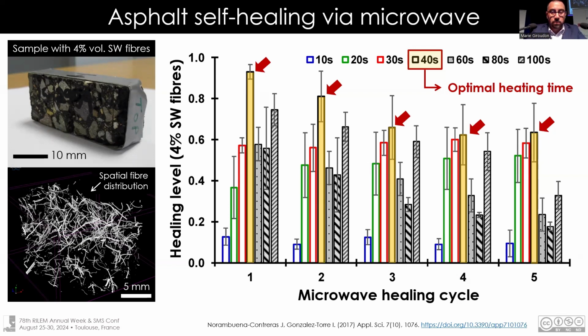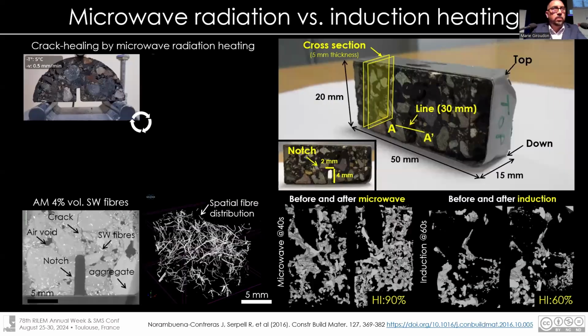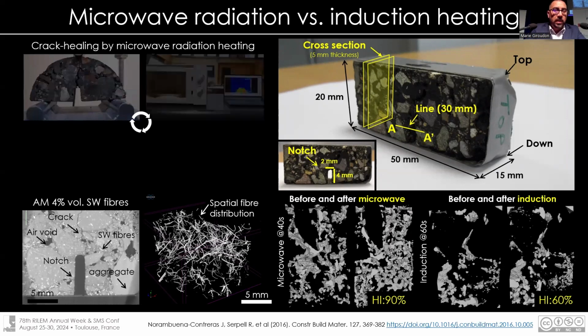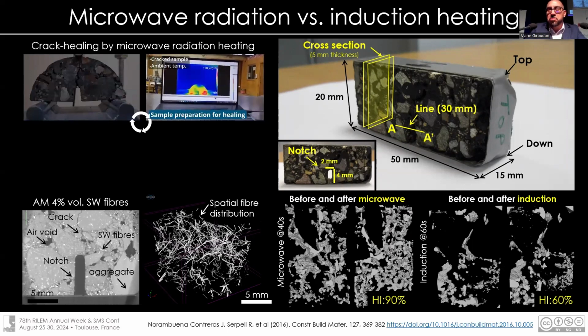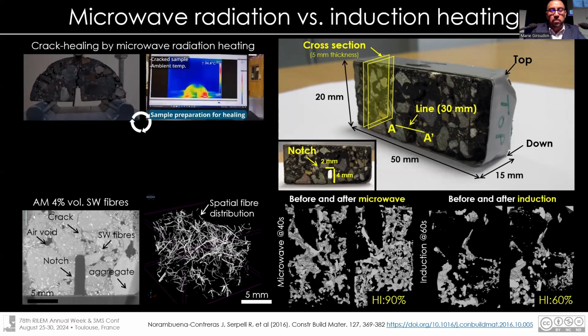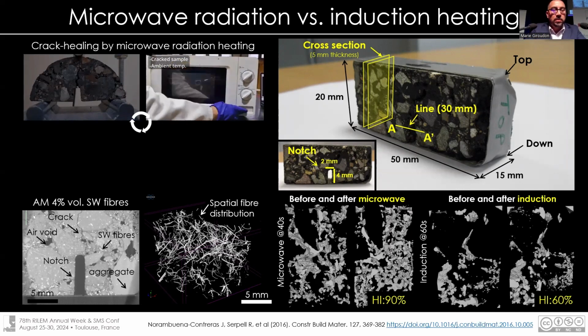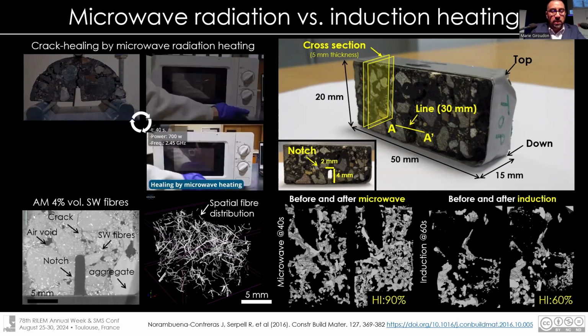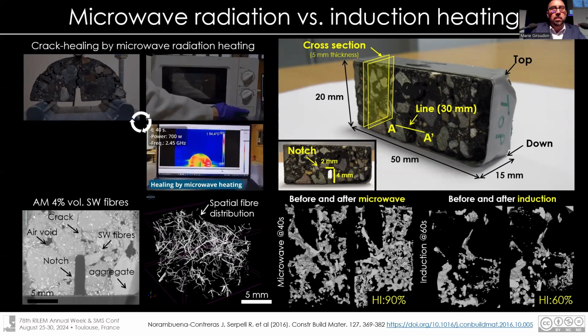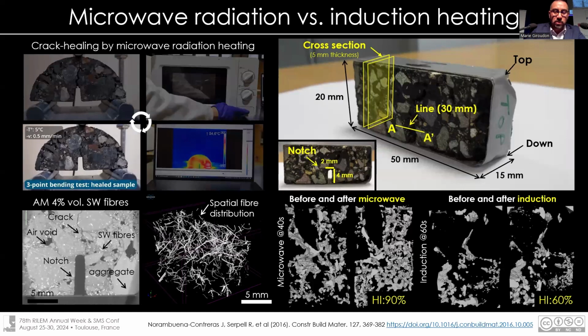For that purpose, it's necessary to design pretty easy tests in the lab. Basically, in a microwave oven, you can heat samples. Not your food, please. And after that, you can evaluate using a camera the temperature distribution inside the material over a specific time, in order to evaluate the crack closing autonomously by the effect of the microwave radiation. And also you can compare this result, this time, and this energy with the induction technology.